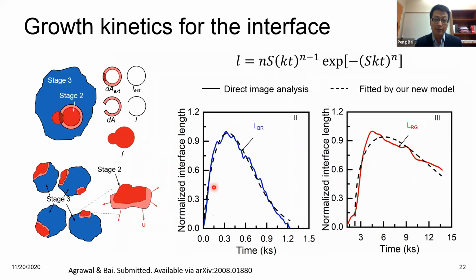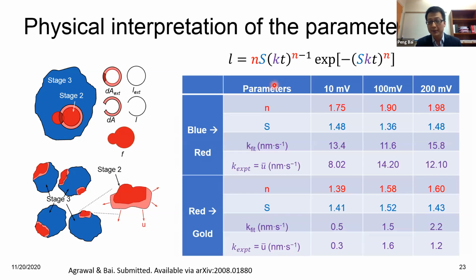So here, the red one, these two figures really just came from the interface we characterized. You can see here, we developed a model showing up here that can accurately fit the curves. And it is actually based on the very famous, widely used growth theory. But there are differences. The general growth theory can definitely fit the curve, but you cannot explain the parameters. To make any fitting physically reasonable, you always have to go back to the parameters to see what is going on with that. So here, let me explain our model a little bit.